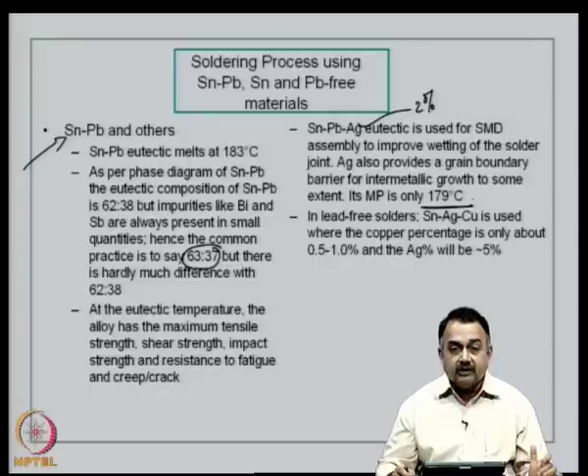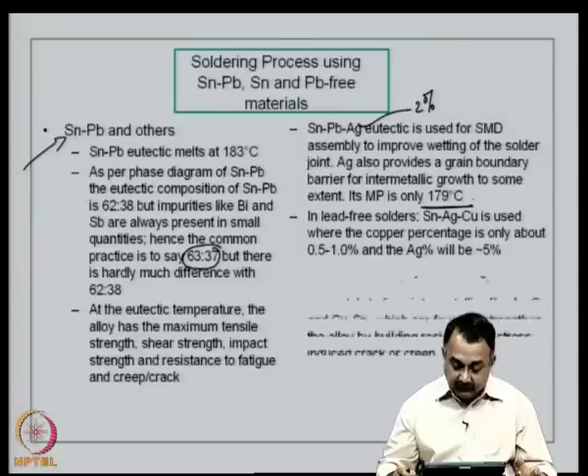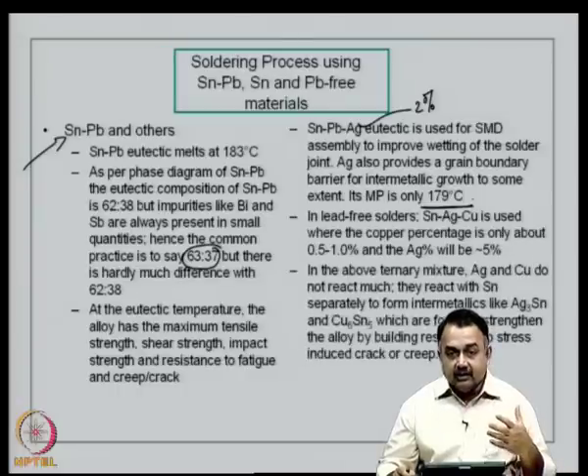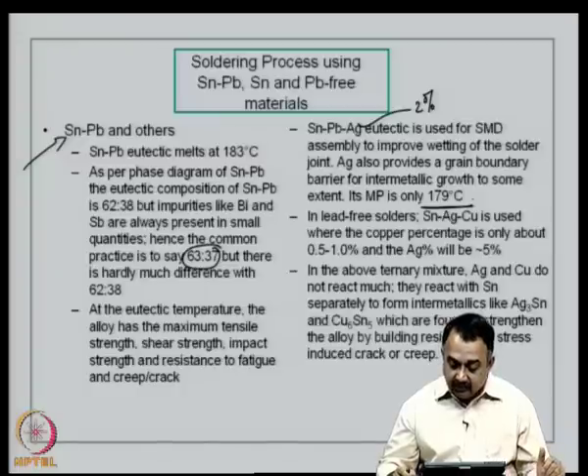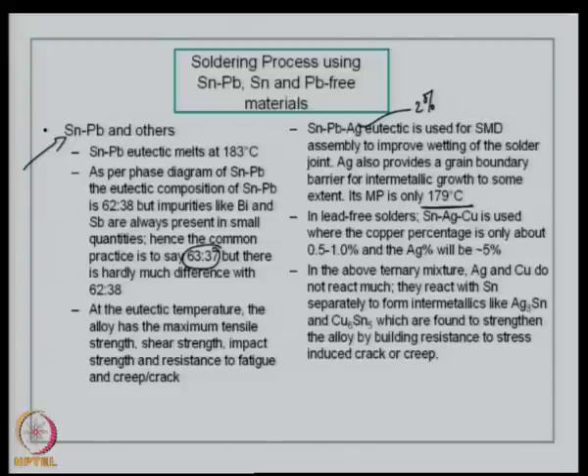In lead free solders, tin silver copper is used, okay, very popular, where the copper percentage is only about 0.5 to 1%, and silver will be around 5%. In the above ternary mixture, that is the tin silver copper ternary mixture, silver and copper do not react much. They react with tin separately to form intermetallic phases, like Ag3Sn or Cu6Sn5, which are found in literature to strengthen the alloy by building resistance to stress or fatigue or stress induced crack or creep, which means the reliability of this system is definitely much better compared to other systems.